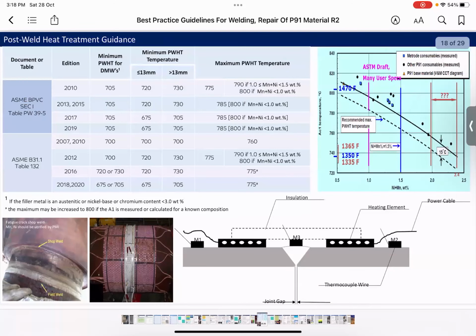So this illustration is for PWHT and the distribution of thermocouple and heating element. We can see that this weld has resulted in cracking in the weld because the Mn and Ni elements were not verified, and resulted in type 4 cracking in the weld.